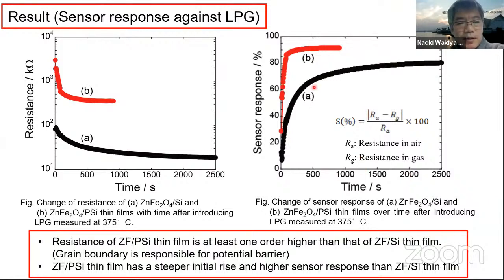And this is a sensor. This is the sensor properties for LPG. A is for the zinc ferrite thin film on silicon substrate, and B is the zinc ferrite thin film on porous silicon. After introducing LPG gas, measured at 375 degrees C, the resistance of the zinc ferrite porous silicon thin film is at least one order higher than that of zinc ferrite on silicon substrate. This suggests that the grain boundary is responsible for the potential barrier, and this is the sensor response.